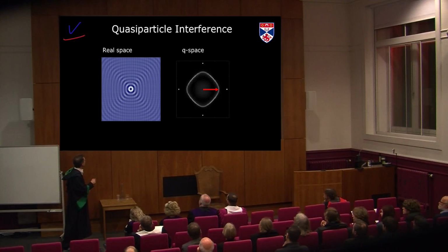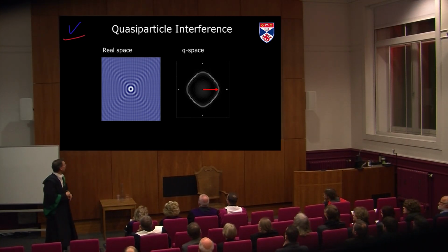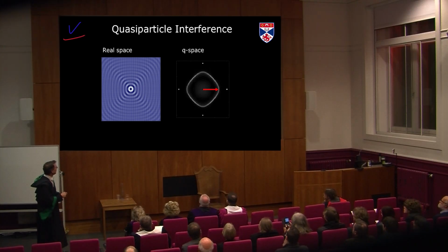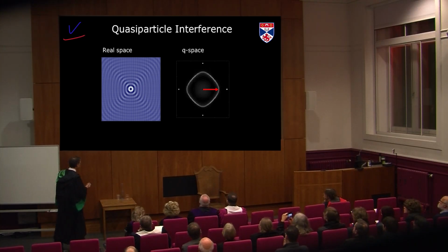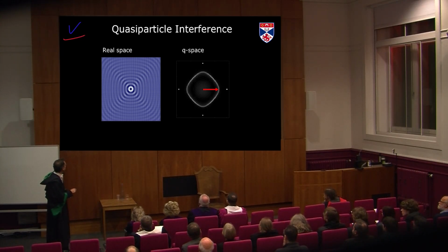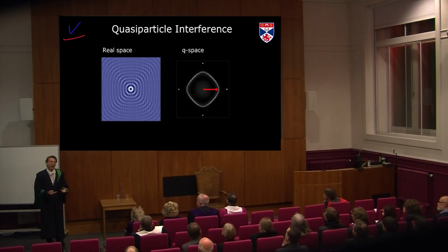So there's one atom missing here, and then these ripples. And then we take the Fourier transformation, which is shown here. And now basically anything which is periodic in the image on the left is a point on the right. So this atomic square lattice here are these points here, because it's periodic. And these ripples which you see here become the square ring here. And that's how we can analyze what the electrons do in the material.